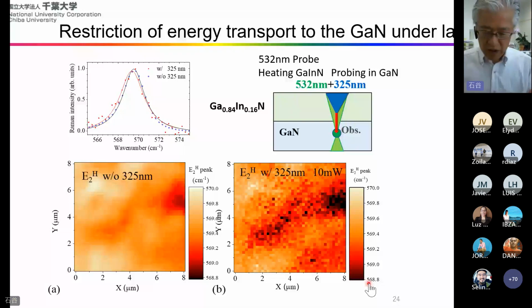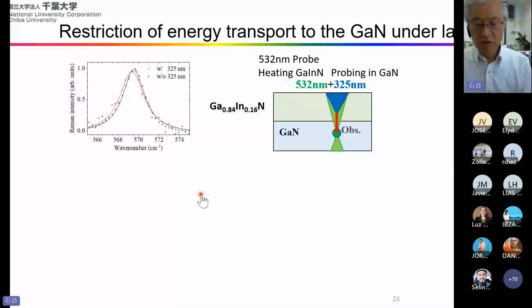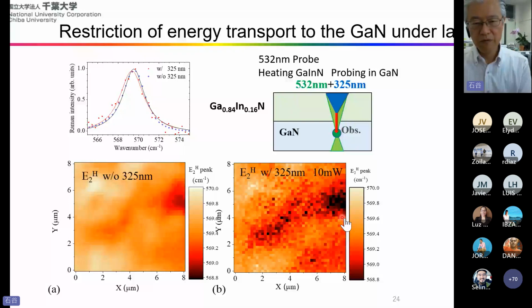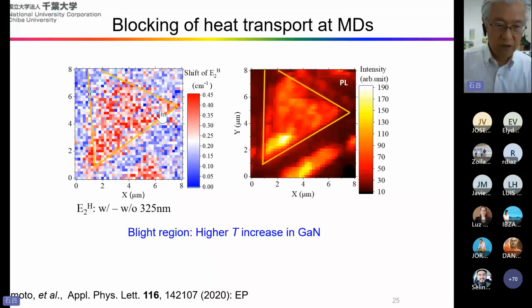But we cannot see any triangle structure. But when we take the difference of this image, at the same position, we can see this triangle structure. This is a photoluminescence image, and in the photoluminescence image we can also observe the same structure. But in this case, by the upper layer, the gallium indium nitride upper layer, this is monitored, while the underlayer is monitored here. So the monitoring layer is different between this one and this one.